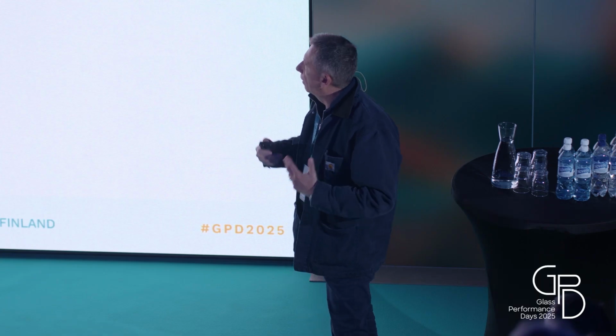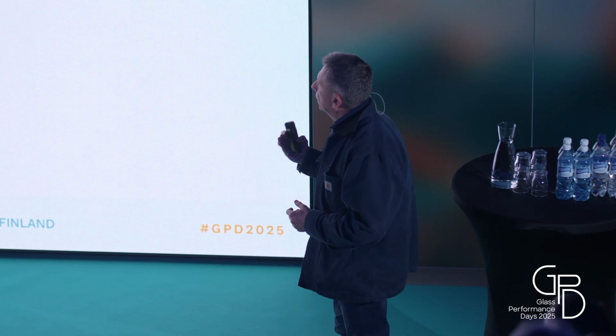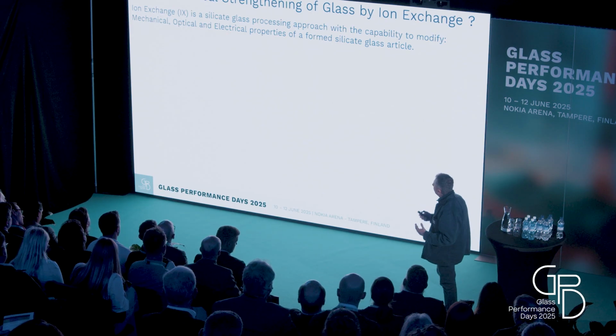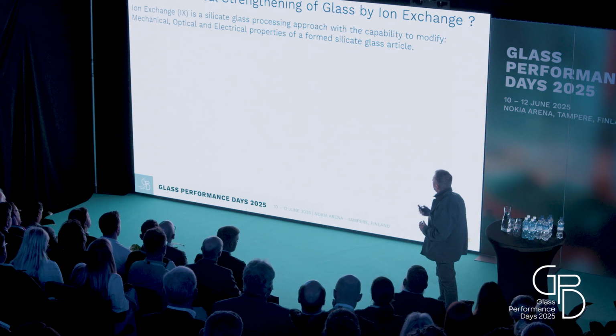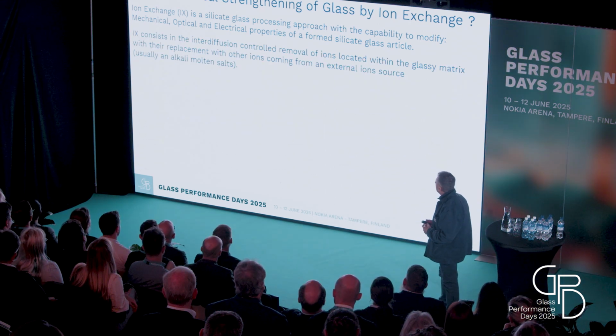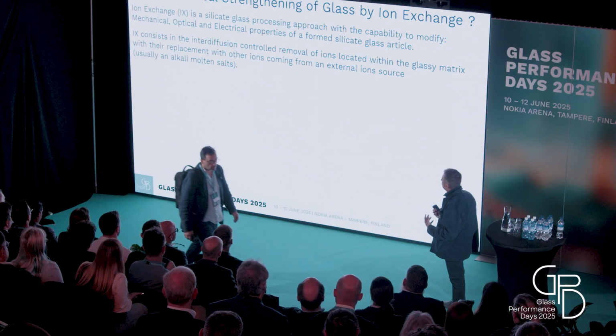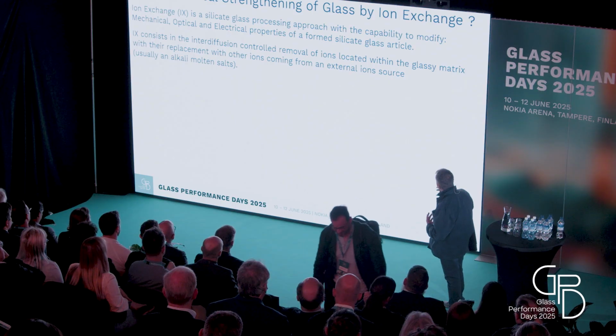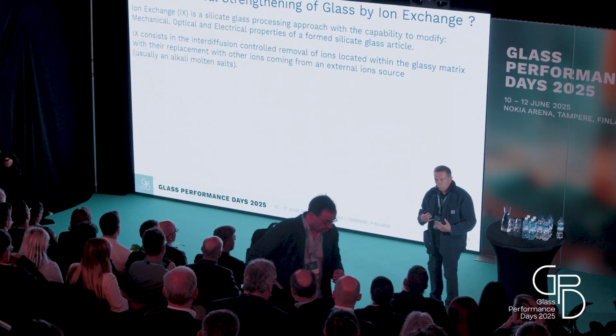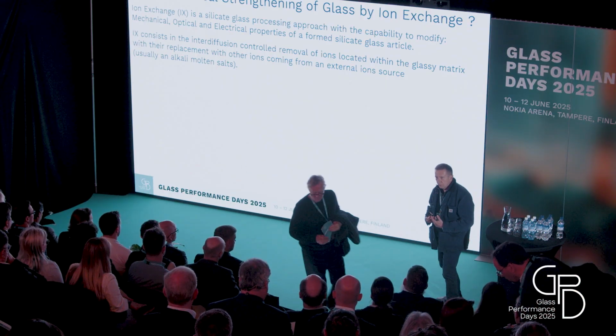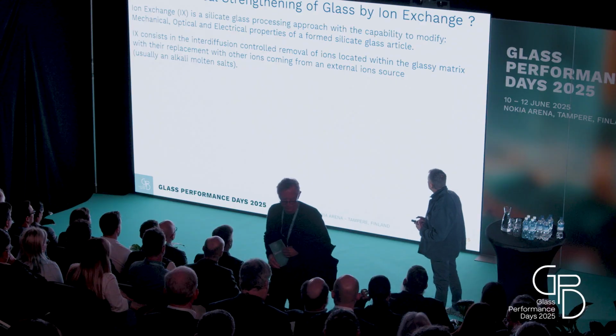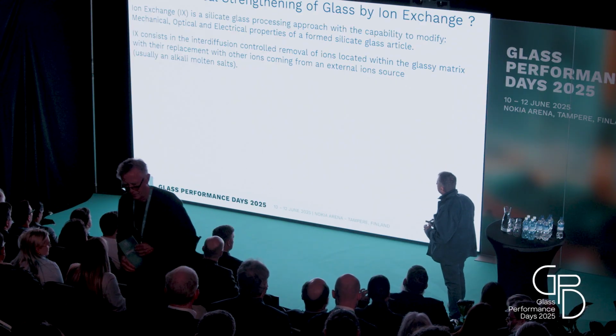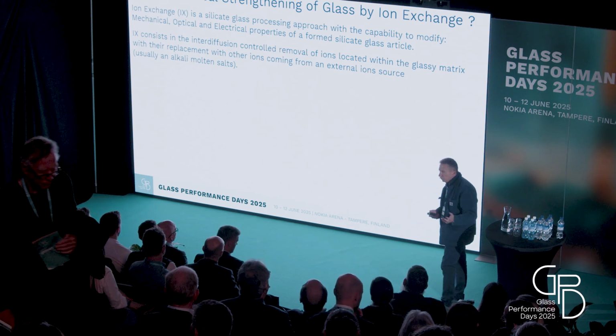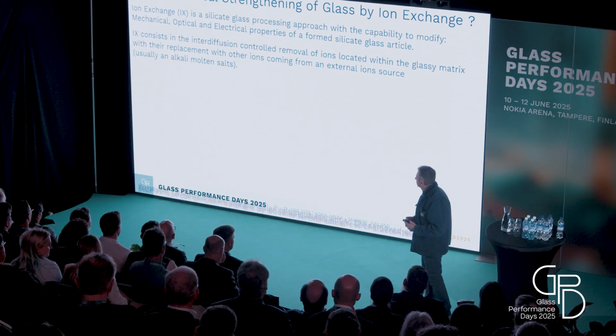Why chemical strengthening of glass by ion exchange? Maybe not all of you are familiar with this type of process and technology. So ion exchange is a silicate glass processing approach with the capability to modify the mechanical, optical, and electrical properties of a formed silicate glass article. It consists in the interdiffusion controlled removal of ions located within the glass matrix. What is going to be removed, obviously, is not silicon, is not oxygen, but the modifiers, namely sodium in this case. And this removal will be followed by their replacement with other ions coming from an external ion source, in this case alkali nitrate molten salts.